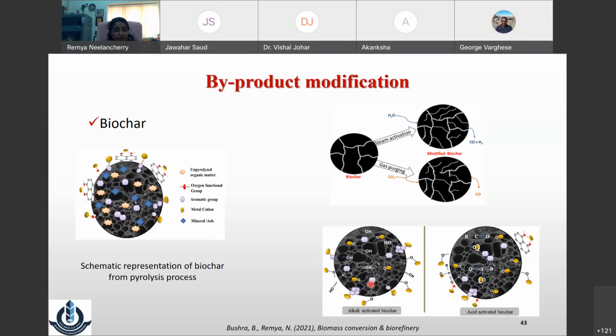Right? But to further improve the biochar property, we are again post-modifying the biochar, either just by steam activation or gas purging. This is done just to improve the pores that are blocked by the amorphous carbon during the pyrolysis process. And you can even think of other modification processes like alkali modification or acid modification. In either of these, we can play with the surface functional groups. So it may have more OH groups or more carboxyl groups based on whether you are going for alkali or acid modification. And this can be used for the removal of other opponent ions from the wastewater.